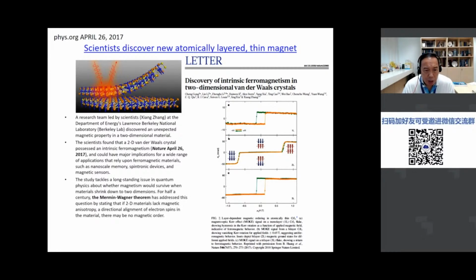And this study was important because it tackled a long-standing issue in quantum physics about whether magnetism would survive when you shrink a material from 3D to 2D. Because for half a century, the Mermin-Wagner theorem addressed this question by stating that 2D materials lack what is known as magnetic anisotropy, and because of a directional alignment of electron spins in the material, there may be no magnetic order. So this study really addressed this theorem. And the key to this study was they found that you have to create some magnetic anisotropy in a 2D material before you can get intrinsic magnetism.